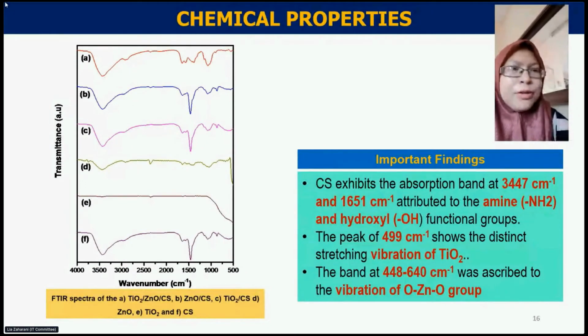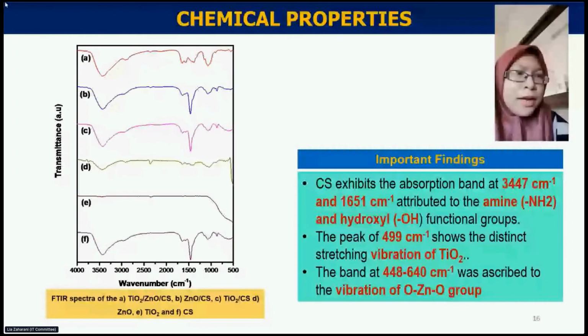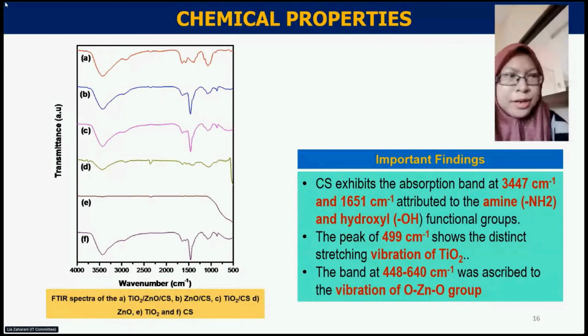The peak at 499 shows the distinct stretching vibration of the TiO2. The band of the TiO2-chitosan, meaning the connection band of the TiO2 and chitosan, reveals the characteristics of both chitosan and titanium oxide. The strong peak at 3441 is shifted to a lower wavenumber, which corresponds to the stretching vibration of the hydroxyl and the primary amine groups, and becomes broader, indicating some interactions between these groups and the titanium oxide.